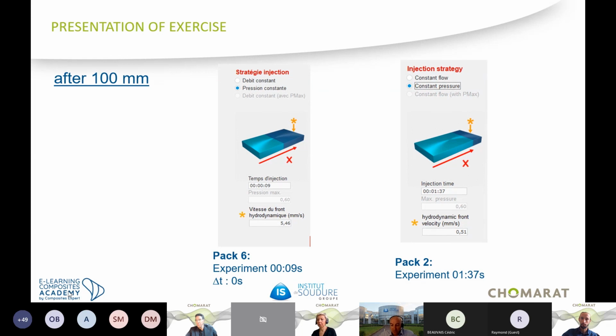And below the image, you will get access to the result of the experiment, the real experiment that will be done by the training. So at the first stage, at 100 millimeter, we see that right away we have a difference in terms of impregnation time with and without G-flow. So few seconds with the G-flow that will give very high speed of impregnation. That is not the case without G-flow, so without flow media included in the laminate.